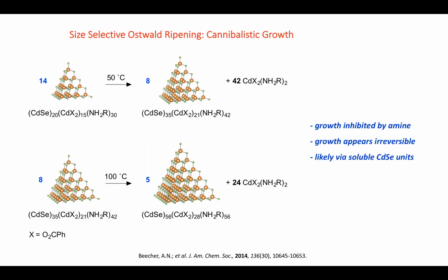The presence of ligands stabilizes these crystals. If you have a higher concentration of ligands, the crystals are less likely to grow. And this implies that the growth is a falling apart kind of a mechanism. The binding and coverage of ligands, when it increases, the structure becomes more stable. It's not a picking apart mechanism where the ligand comes on and rips parts off.